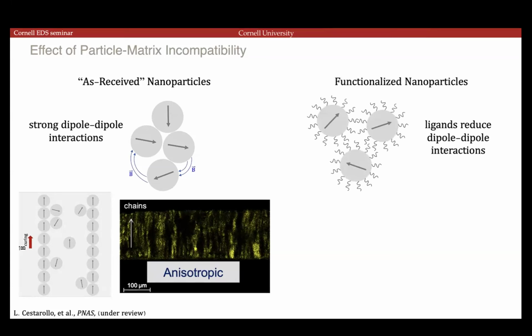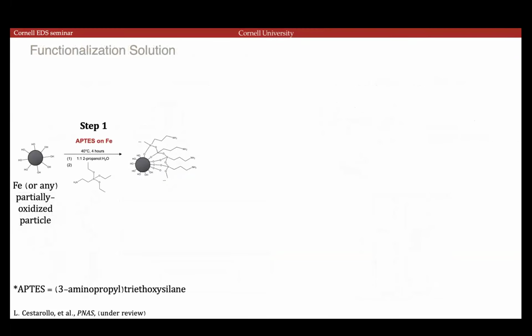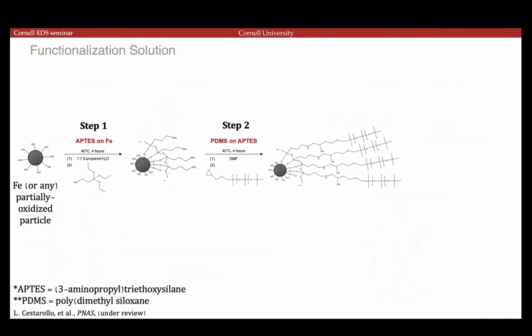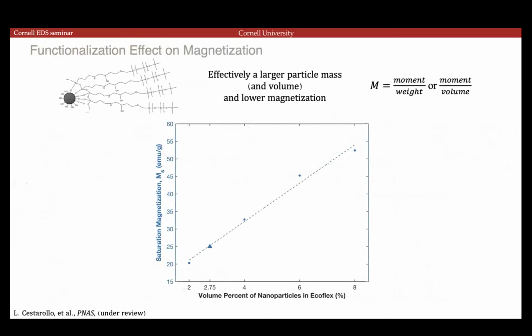So one way to improve this is to functionalize the surfaces and have these longer ligands that separate the particles. Then the interaction is weaker, and when we apply an external field to align them, they can actually respond to the magnetic field and align properly, and then we should get nice cleaner chains. This is some work that we did in collaboration with Professor Lyndon Archer's group in chemical engineering. They attached ligands to our iron nanoparticles and finished that off with PDMS so that it can mix well into our elastomers.